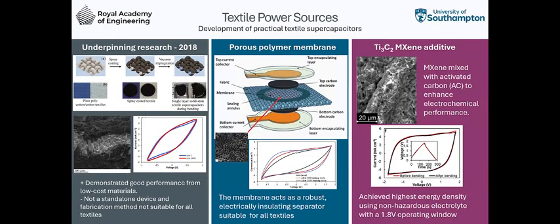So we've done a lot of work over the last few years on turning the textile into an energy storage device. So in this slide, I'm going to just introduce some work on supercapacitors. So on the left here was our first example device where a supercapacitor is basically like a conventional capacitor with two electrodes, but the electrodes are made from special carbon materials that have a very large surface area. So they're a porous carbon material. In this case, it's called activated carbon, which is a very low cost, widely available carbon material.